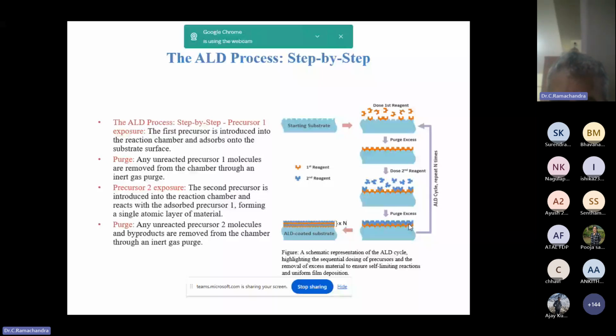One cycle is completed, the chemical reaction stops, because this is a surface-limited chemical reaction. The precursor is adsorbed by the surface, then reacts with the chemicals. Once the reaction is completed, there is no further reaction. Already it is saturated until I apply another cycle. Therefore, in a given cycle, only one atomic layer is deposited. It is a self-limiting chemical reaction, a surface reaction. This is excellent in controlling the thickness of the thin film.